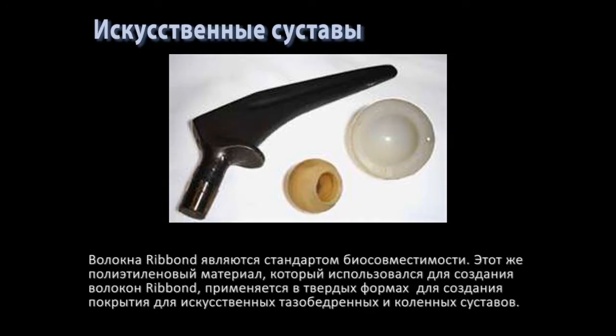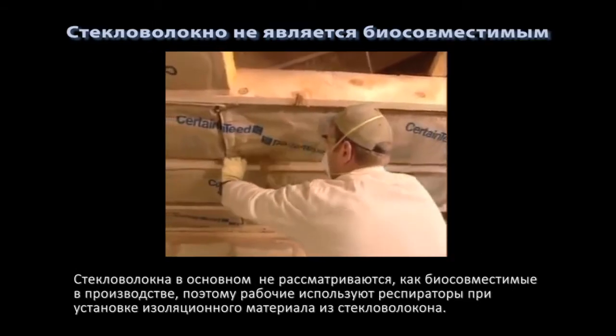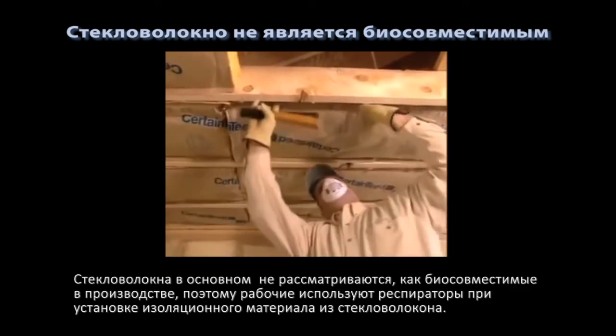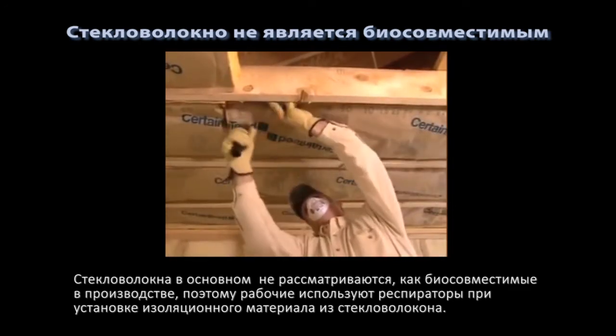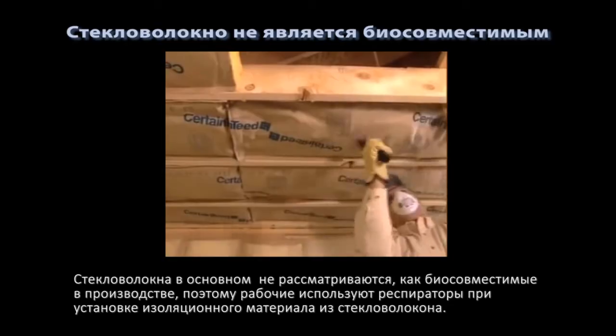Ribbond's fibers are the standard in biocompatibility. The same polyethylene material used to make Ribbond is used in solid form to make the liners for artificial hip and knee joints. Glass fibers are generally not considered biocompatible in industry, which is why workers use respirators when installing fiberglass insulation. Some marketers of glass fiber reinforcements state that you can polish glass fibers and that Ribbond cannot be polished. This is partially true.